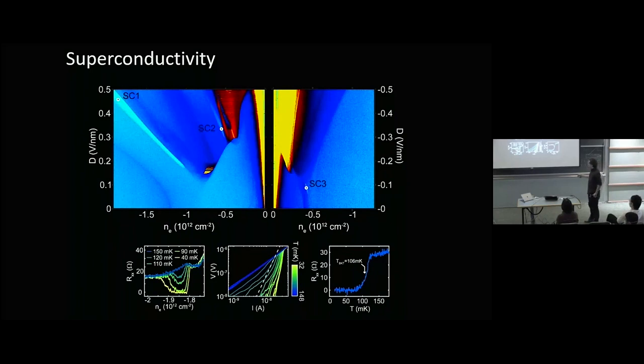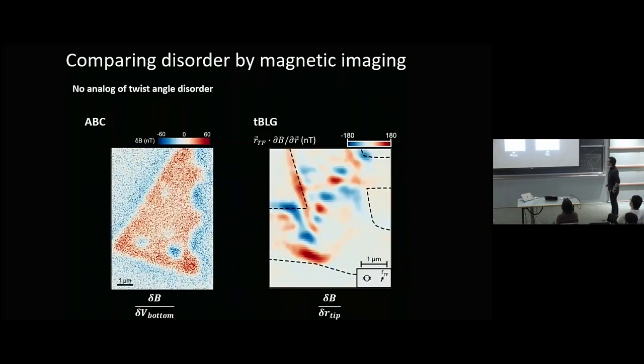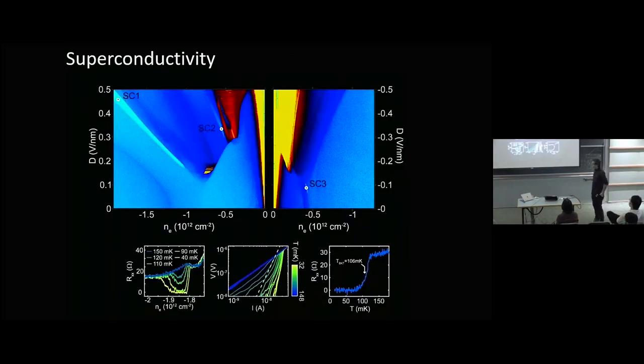TC is relatively low for ABC, right? The highest TC is superconductor 1, which is sort of the best form. It's about 100 millikelvin. Okay, superconductor 2 is more like 30 millikelvin, as is superconductor 3. They're both sort of relatively low TCs. Now, I'm going to tell you about some of these superconductors and give you kind of a summary. I'm not going to try to tell you about all of them because at this point it's like 3 or 4 or 5 papers and it's more than I can fit in this talk.